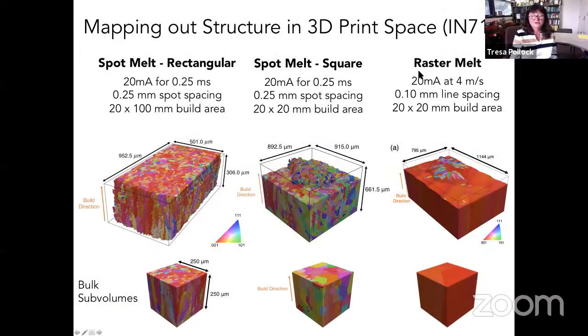Okay, so for those same 3 conditions, I show you 3D data sets here. And the first thing that you'll notice, we're looking at electron backscatter diffraction data. And these are the grain orientations relative to the build direction. And so the first thing you'll notice is that in these 3 different builds we have a completely different grain structure in spite of these near constant processing conditions. And I'll say a little bit about each one of these data sets and emphasize the things that we can learn from being able to look at the structure in 3D.